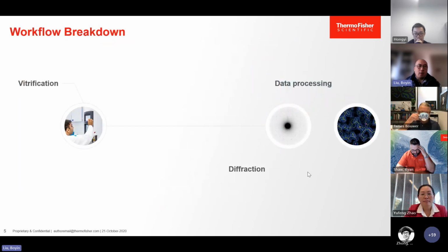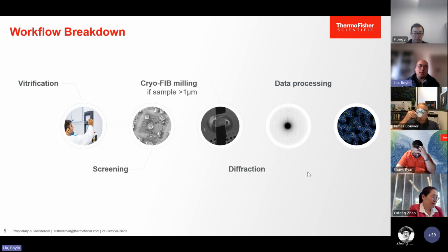I'll just break down the workflow. Hong has already explained the workflow. So basically, for protein crystals, we do vitrification of the protein, then put it in the TEM and collect data. But sometimes when the crystals are too big, we use other mechanical methods to grind the crystals to smaller sizes, or sometimes we use a method called cryo-FIB milling to create a thin crystal lamella.